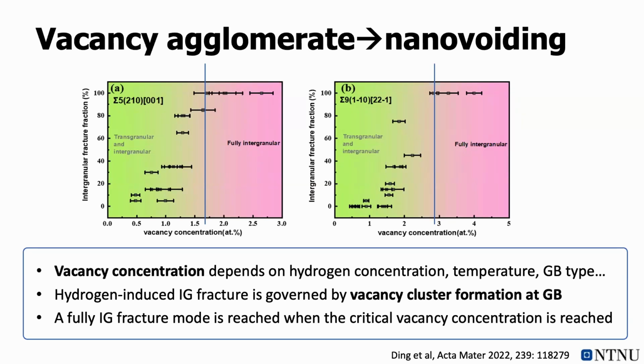And with those intergranular fracture maps, we can predict at which hydrogen concentration, at what temperature, and when your material will have fully intergranular fracture. So that means it is more dangerous to the performance of the parts.